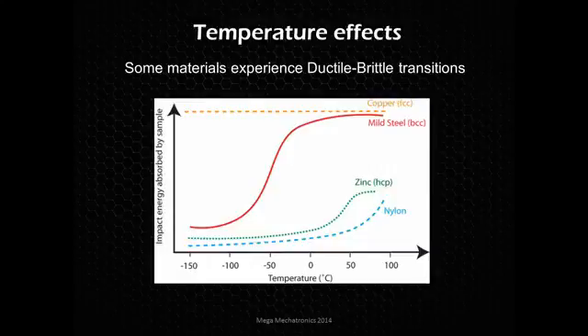So you see up top the copper, it actually maintains its ductility across a wide range of temperatures. The copper, and you see the FCC, that's face centered cubic structure, and then the mild steel's body centered cubic structure. So that does affect this ductile brittle transition, where body centered cubic structures exhibit this sort of phenomenon. So you can see the mild steel right around 0 degrees, it starts getting more brittle, and the zinc and nylon are pretty brittle around room temperature.